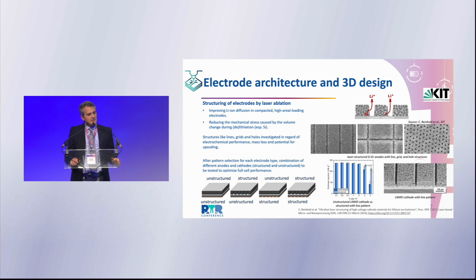the electrode, but at the same time gives some physical room to compensate for the material deformation when the electrode is subject to high recharge or high discharge load. This is working particularly well, so we see this as a key technology to extract more performance from the electrode. And you can see in the blue bars in the slide how by laser structuring the electrode, we can significantly diminish the loss of performance at high C.